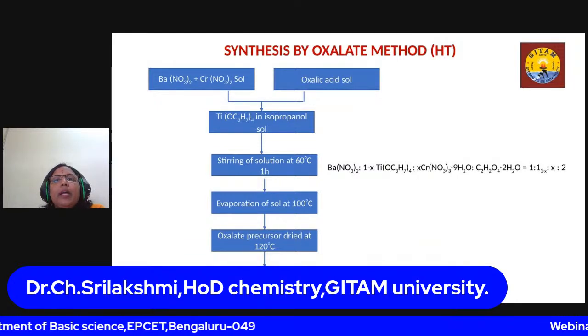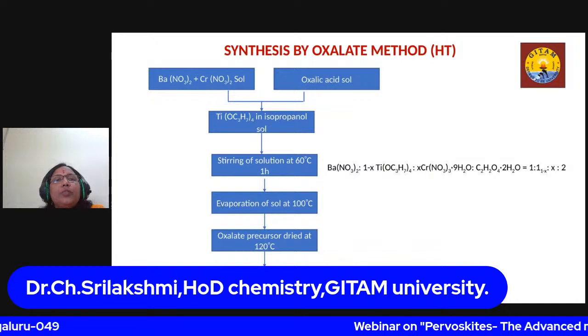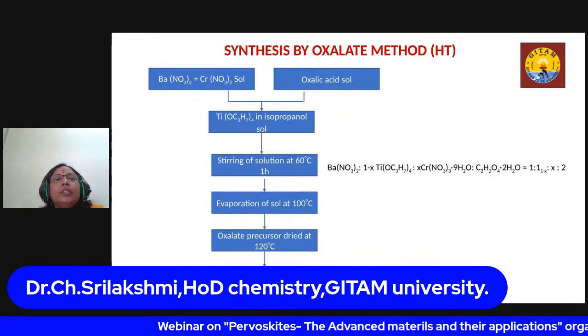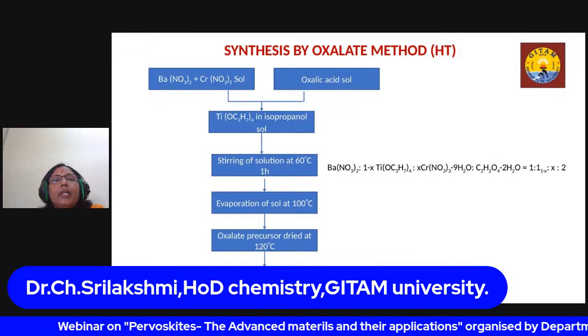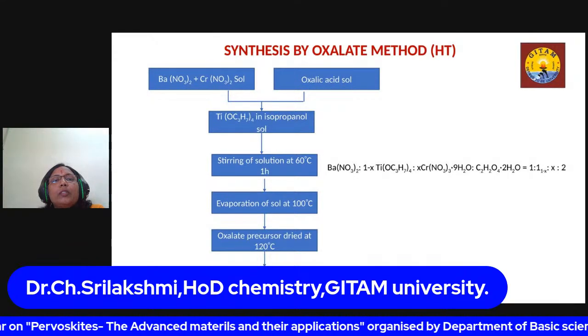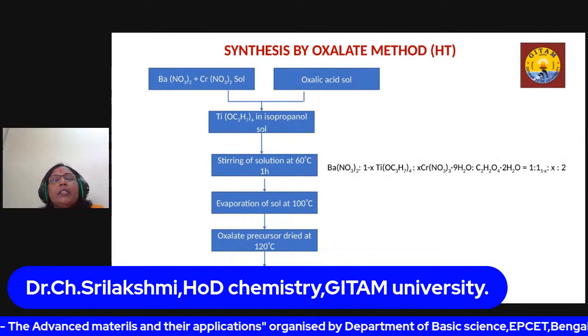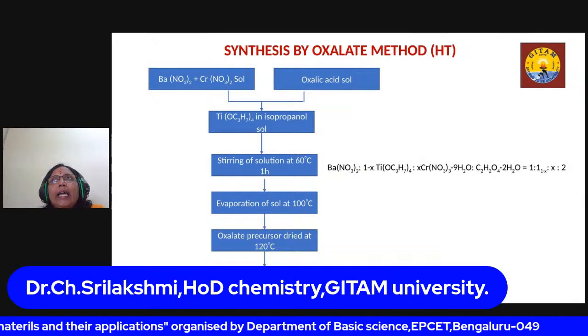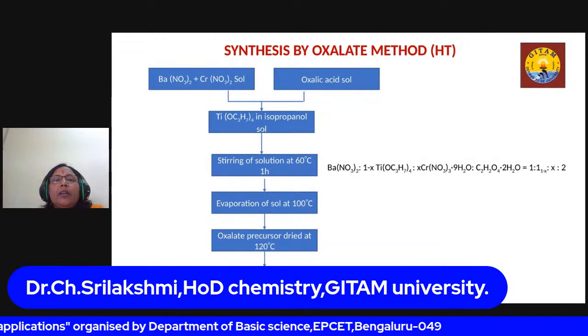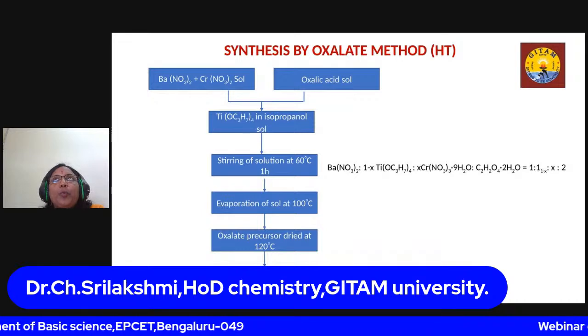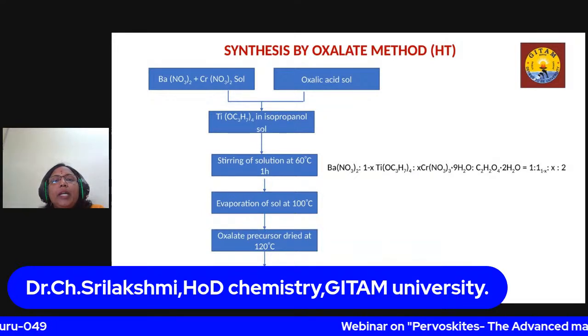And synthesis by high temperature oxalate method. This is the procedure. We use barium nitrate and chromium nitrate as metal precursors, and titanium isopropoxide as a titanium precursor, and I use oxalic acid as a complexing or reducing agent and mix them together in an isopropanol and water mixture, and a homogeneous solution is obtained when stirring at 60 degrees